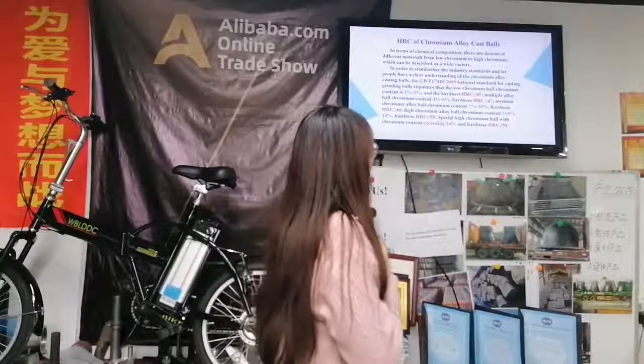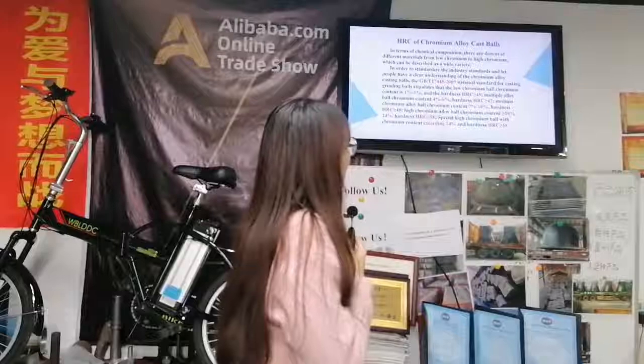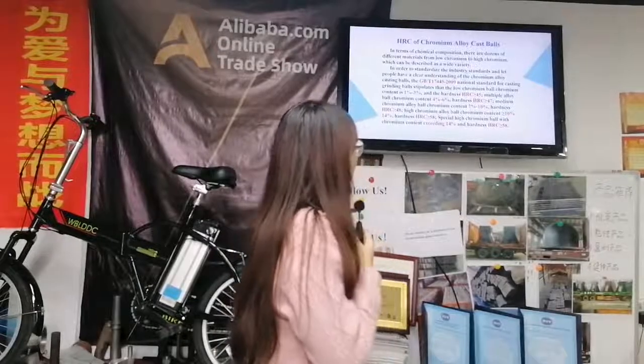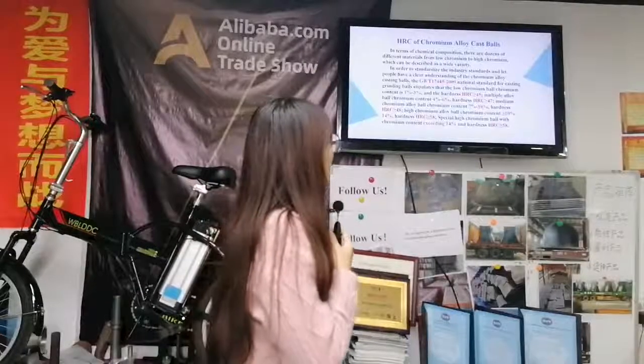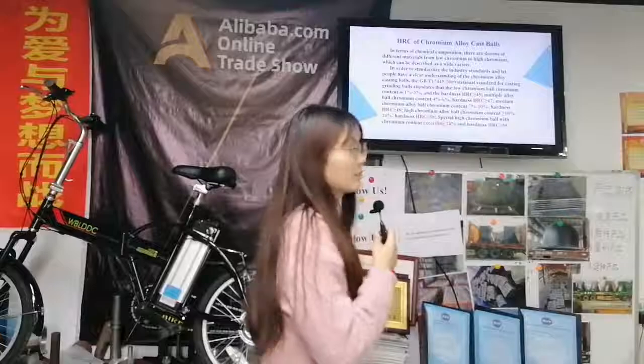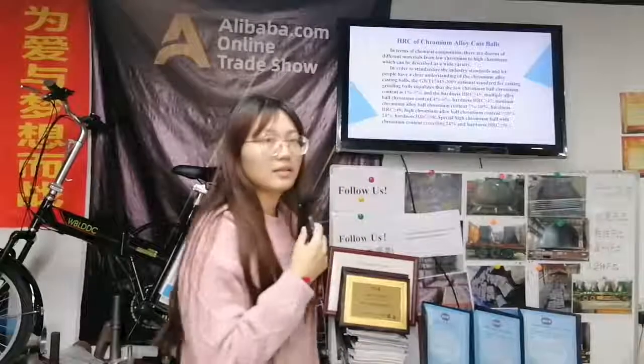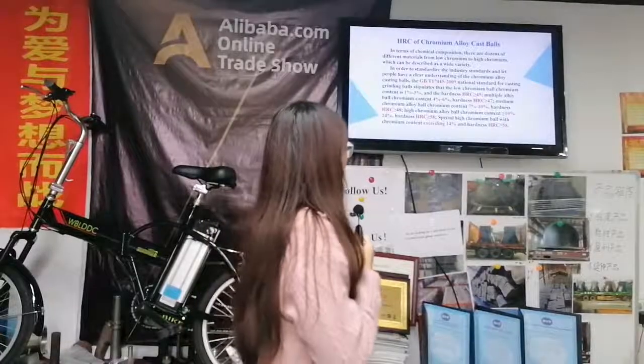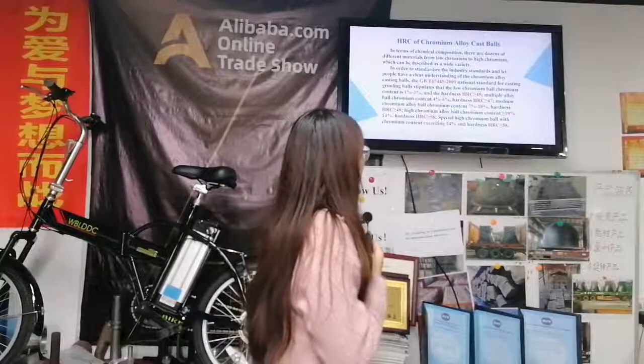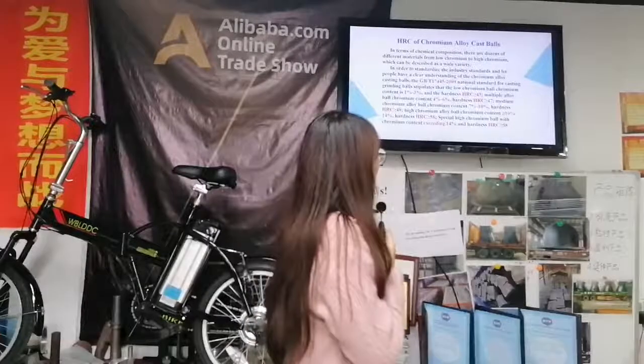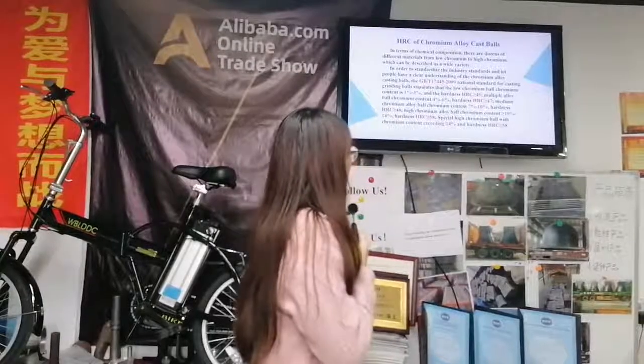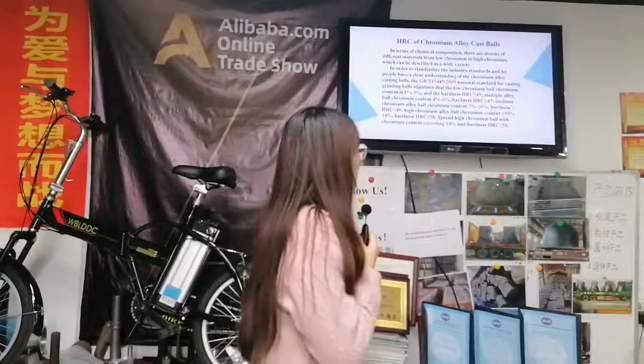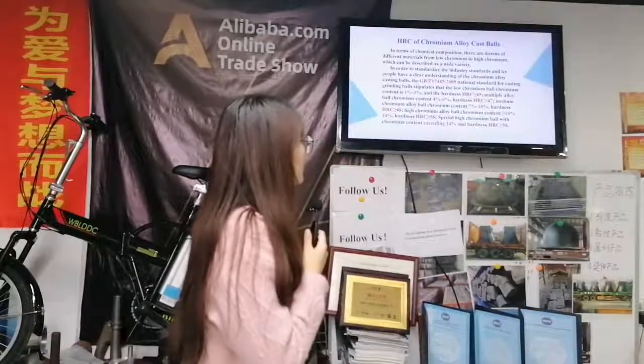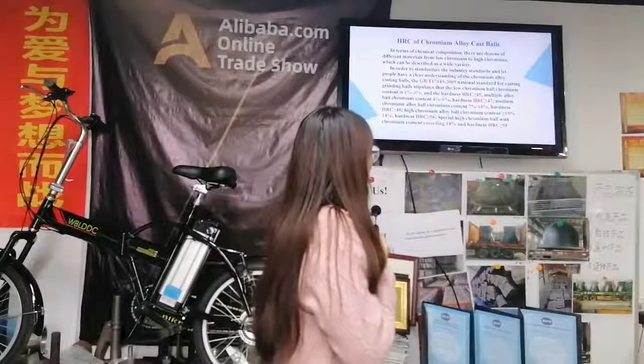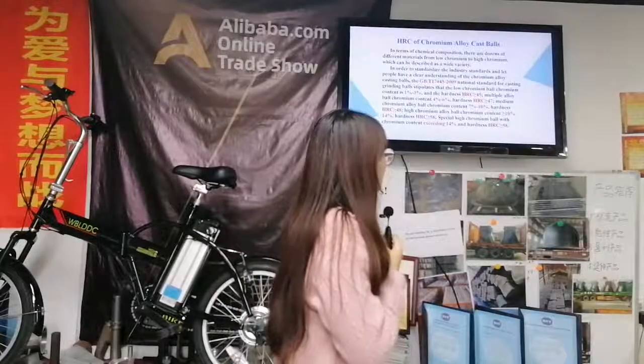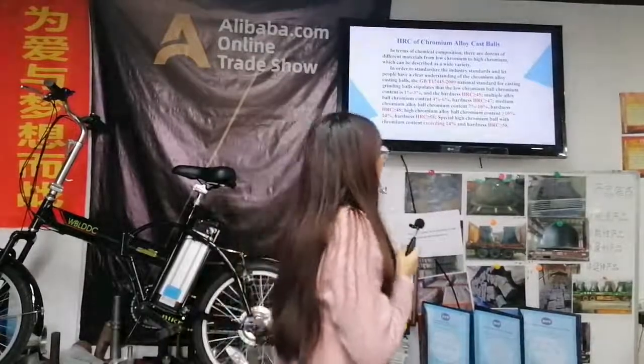Medium chromium alloy with chromium content 7% to 10%. Hardness HRC more than 48. High chromium alloy with chromium content more than 10% to 14%. Hardness HRC more than 58. Special high chromium ball with chromium content exceeding 14% and hardness HRC more than 58.